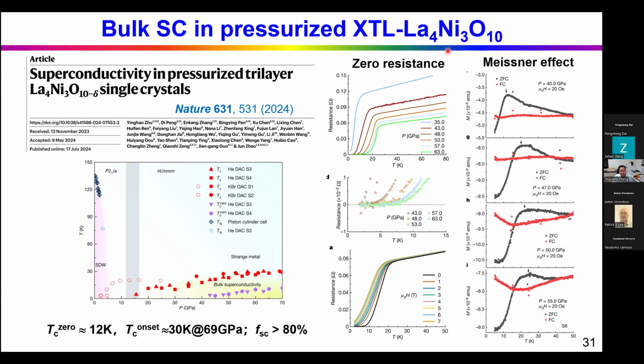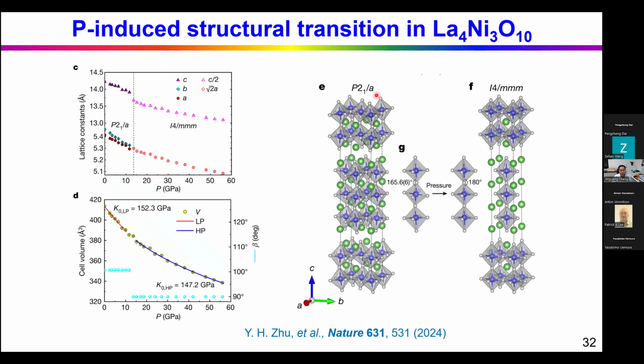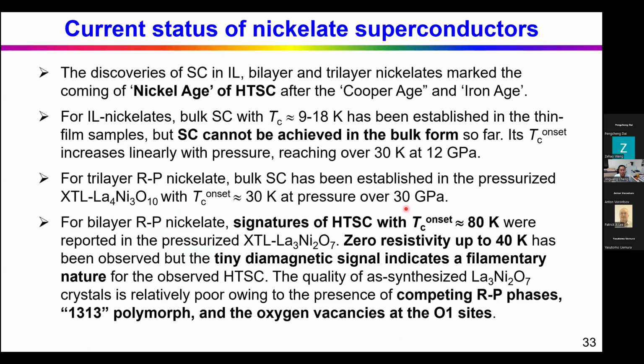But for this trilayer sample, the highest TC onset is about 30 Kelvin, and the zero resistance temperature is about 12 Kelvin. So the onset temperature is much lower than the bilayer phase. Also, this undergoes a structural transition under pressure.